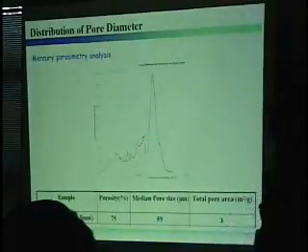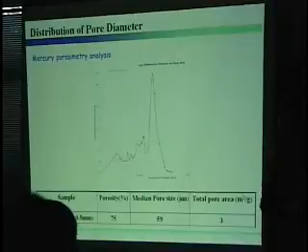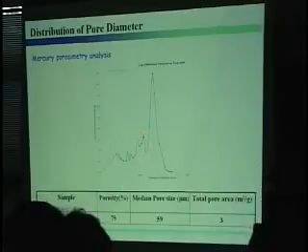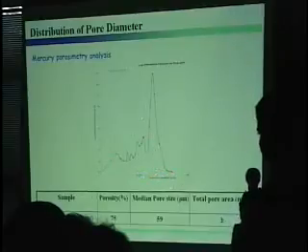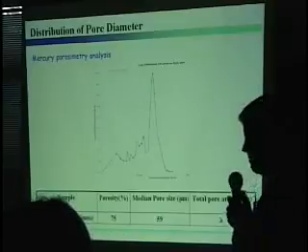And this triblock copolymer electrospun membrane, this is the result from the mercury porosimetry analysis of porosity. Here the membrane thickness used was 0.5 millimeter and the porosity is this much, and these are the results from this instrument, with the pore size distribution around this rough range. This porous electrospun membrane was applied as a cell culture substrate.